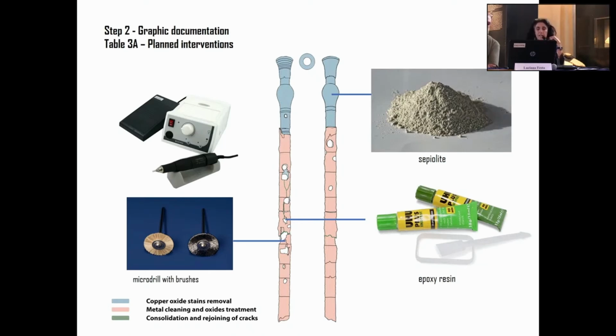And what we plan to do, what we think it will be better to do in this case, is to use sepiolite. This is a kind of clay, very thin clay, mixed with water. It's really very absorbent. And so it's possible to partially, because it's impossible to remove it completely, absorb the metal oxide from the organic material.